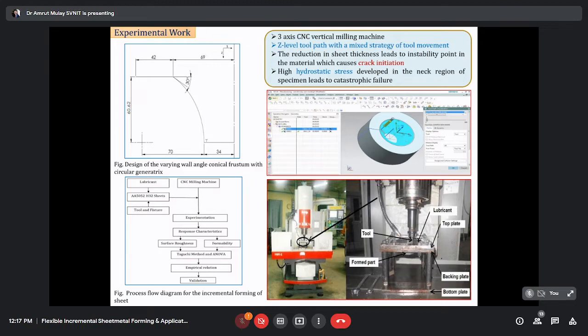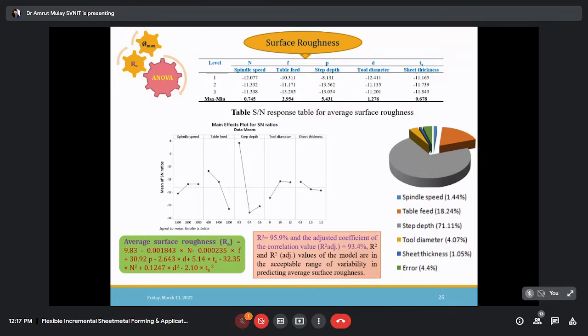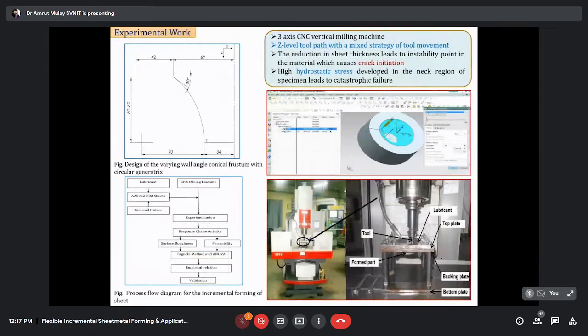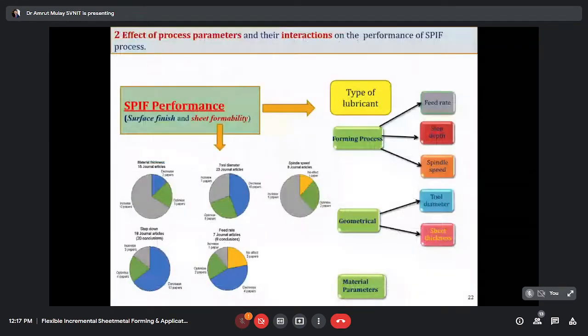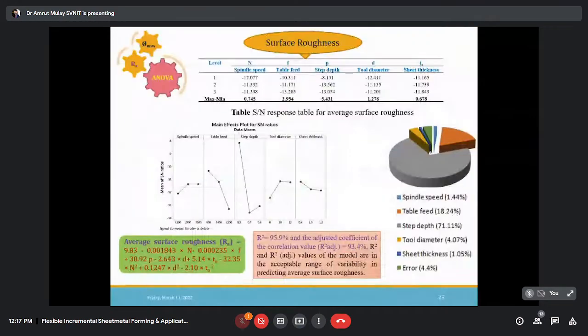So now we use the CNC machine, and when we use the CNC machine, we use some parameters. And these parameters we have investigated, and we found that in case of surface roughness, the effect of, again, I don't go into design matrix and all. Step depth we found a very efficient parameter, and table feed we found a very efficient parameter. So first is step depth. We can see that step depth is a more influential parameter than any other parameter we investigated, right? In case of surface roughness.